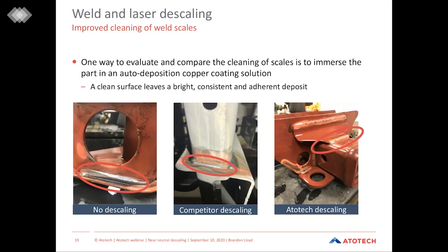So the image on the left, you can see this is a part that has had no descaling done at all. And the coverage on the weld itself is not very good. You can see that it's not bright. It's not complete coverage of the weld itself. As we move further to the right, showing some competitors' descaling processes, again we can see, as we referenced earlier, incomplete descaling of the oxide scale on the weld itself. And this is exhibited from the copper immersion test that we can see here, that there's no coverage of the copper on the weld.